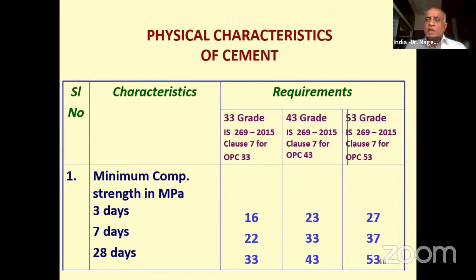So when you cast cement mortar cubes, as per the standard procedure, in the ratio of 1:3, 1 being cement and 3 being the standard sand, using a vibrator which has maintained a RPM of 12,000 plus or minus 400, and casting the mortar cubes for 2 minutes, then keeping it in humidity chamber for 24 hours to prevent the loss of moisture from the cube. Then after that, demolding the cubes and immersing into the water tank, which is maintained at a temperature of 27 plus or minus 2 degrees Celsius. Then these cubes are tested at 3 days, 7 days, and 28 days, and the values we get should be more than what I have shown in this slide.